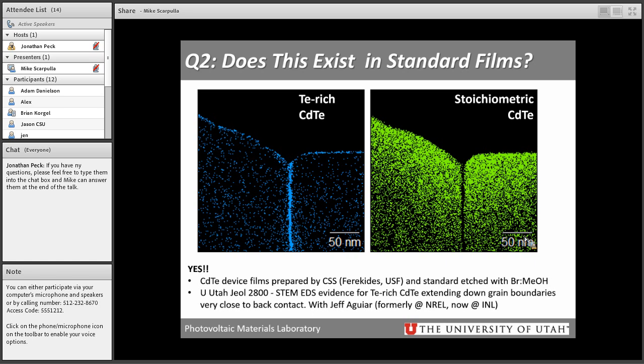And of course, after this, the copper doping needs to happen, but the presence of cadmium vacancies promotes the higher doping by copper acceptors. So you sort of end up in the same place even after the copper doping as what we suppose here.